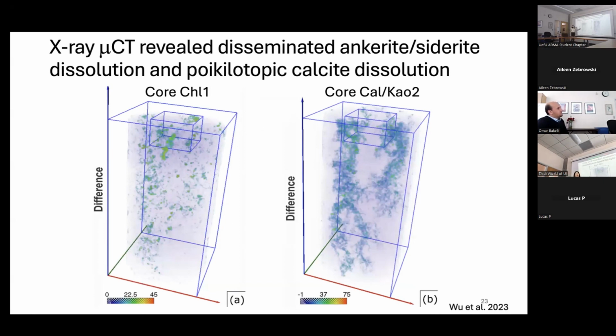This is micro CT images of the difference in pore size of two samples. This one is the one that contains a lot of chlorite. This one contains a lot of chlorite and calcite. So as we saw earlier, calcite tends to dissolve more. So it makes sense that the sample on the right tends to dissolve more, so that you see more preferential pathways. But this one's less. And they do form some dissolution, but those dissolutions are not connected to each other. So they're not big enough to create a new pathway, so there will not be a significant change in permeability in this one and that one.